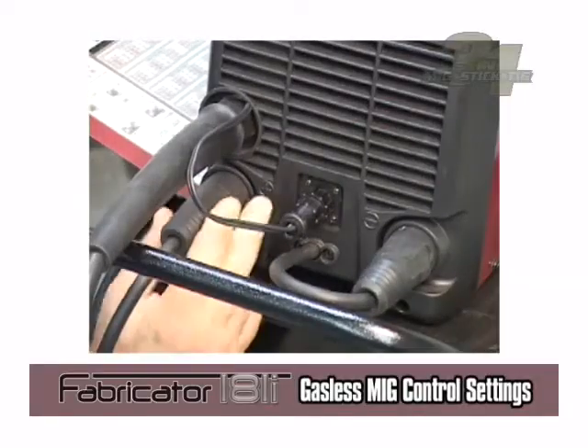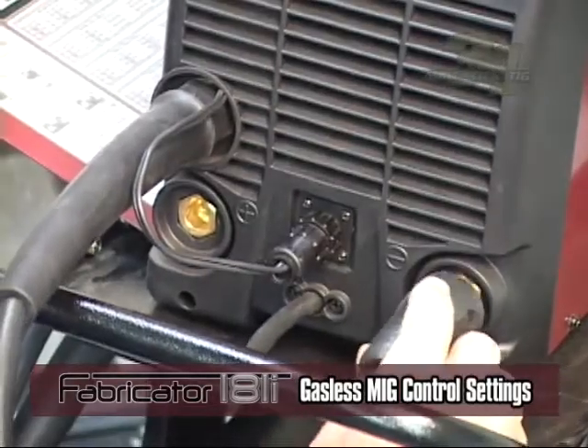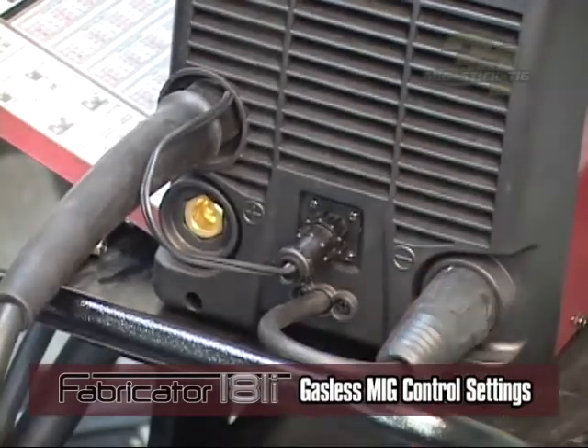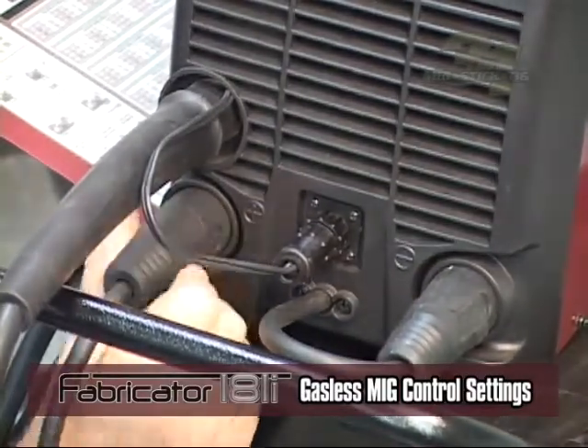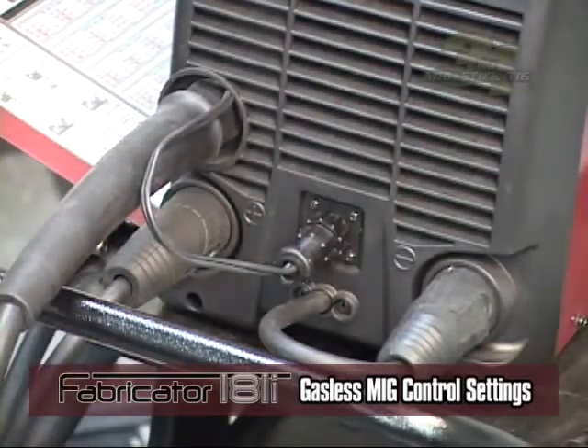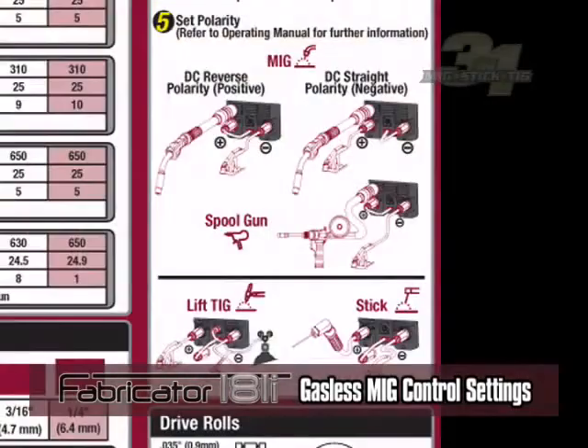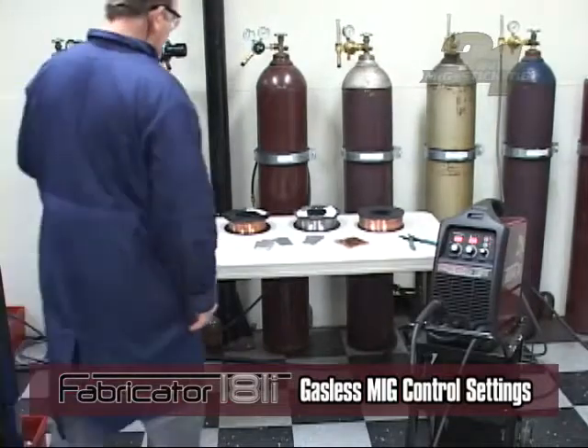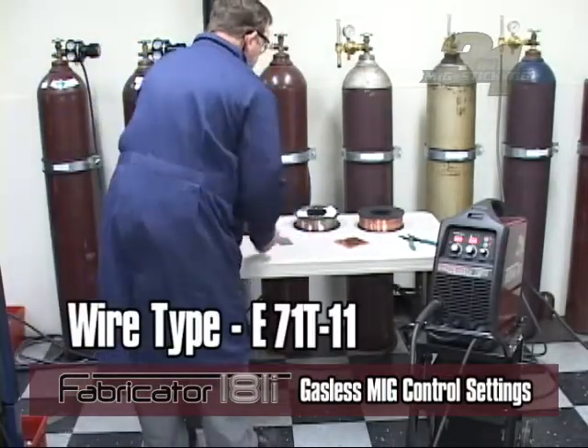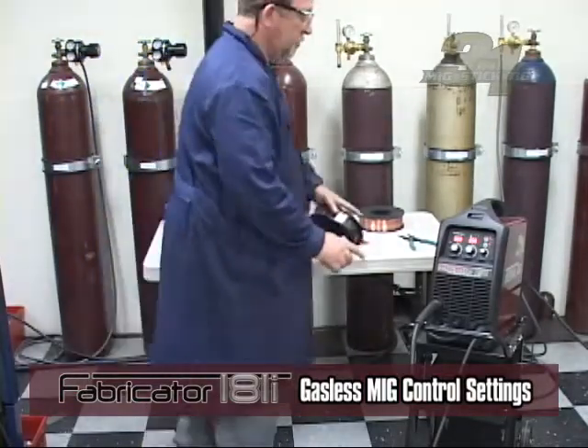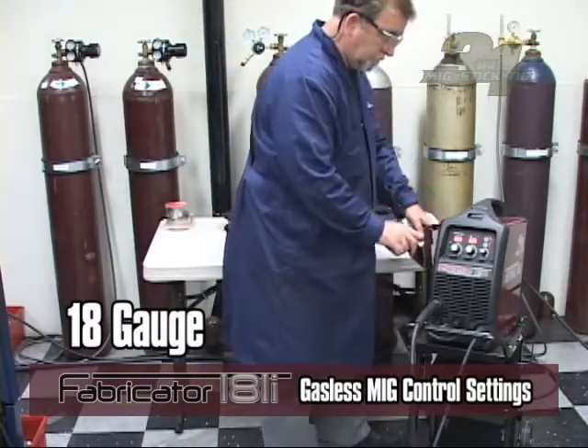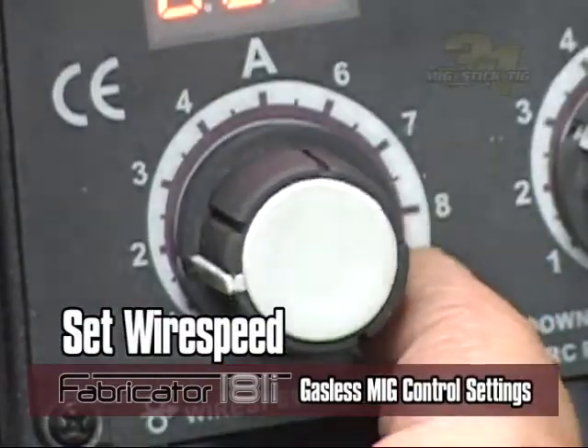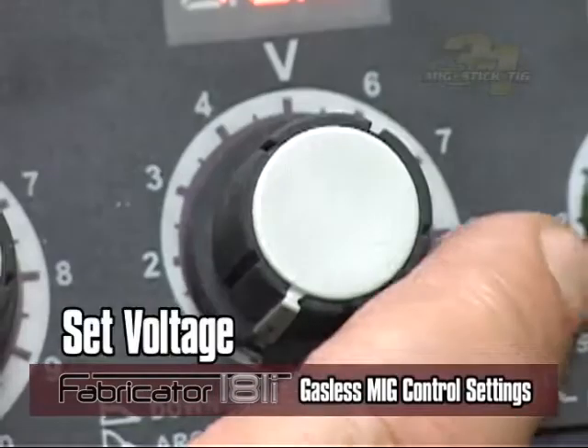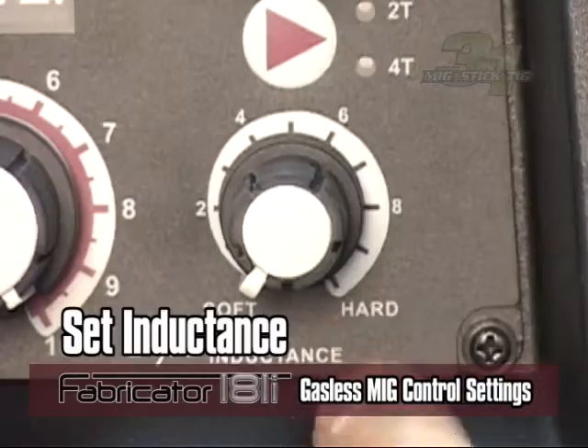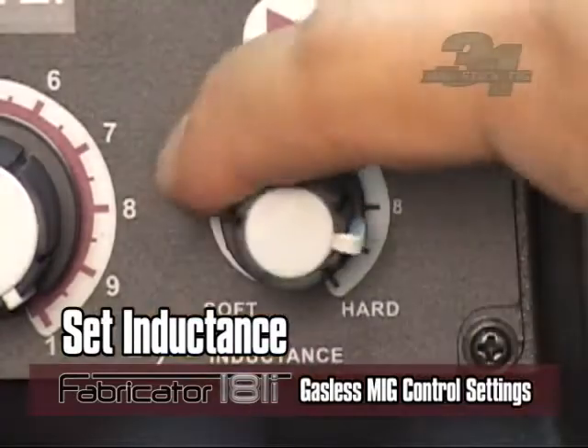MIG welding without gas. For most gasless flux core wires, the MIG torch polarity lead and the work lead are reversed for MIG welding without gas. Switch these leads before setting the controls. See the setup chart. For example, using wire type E71T11 with a diameter of 30 thousandths and a base material thickness of 18 gauge, your wire feed speed would be set at 160 inches per minute, voltage would be set at 15 volts, and inductance set to 10. You would not use a shielding gas.